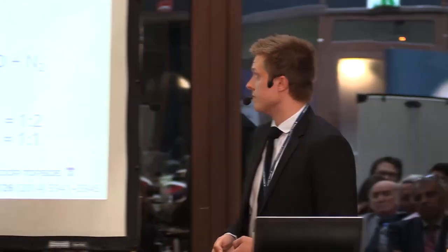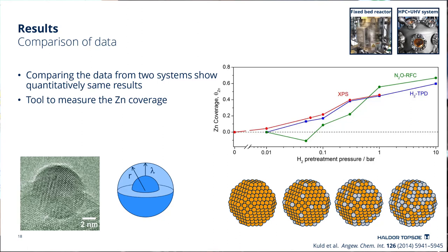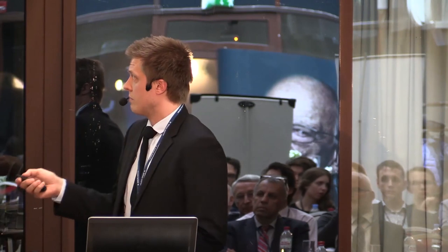But in the case where you have zinc in the surface, you actually have only one zinc reacting with an oxygen, instead of two copper atoms. So this is really why you have this huge difference here. By making a small geometric model, you can actually compare the results for the two different systems. And here it's converted into a zinc coverage on your copper particles. And here we can see the results for the XPS and the N2O and the hydrogen TPD as a function of the partial pressure of hydrogen. And you can see that all these three independent ways of characterizing the systems are returning essentially the same value.